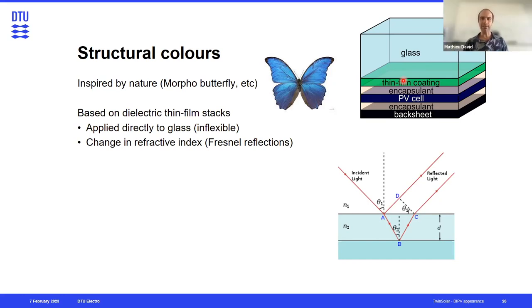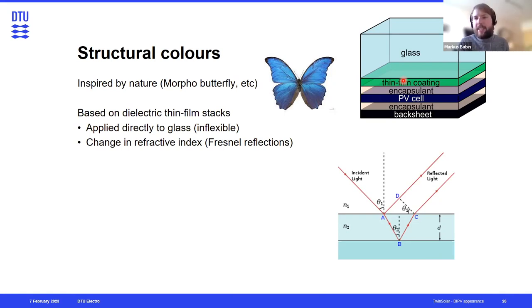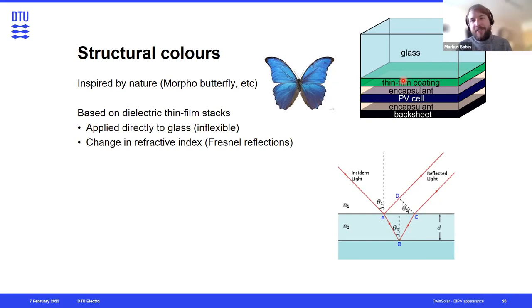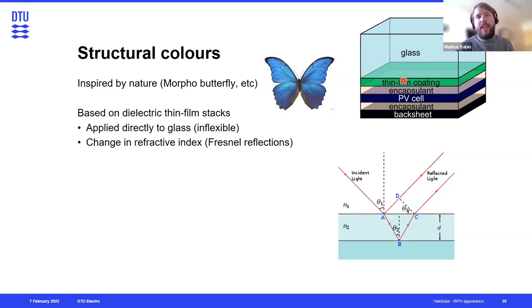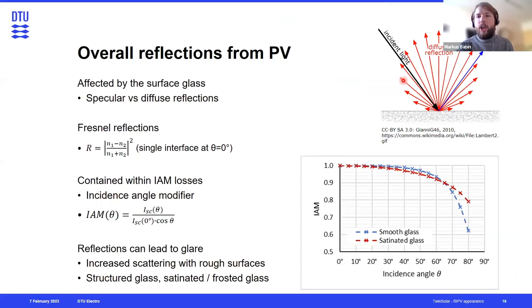Second question: a good glass-on-layer stack with glass, encapsulant, and so on has very high transparency and very low reflection — this is an ideal encapsulant. But are high transparency and low reflection opposite targets? I would say the target is less to have low reflections but rather to have low specular reflections. If you diffuse the reflection — scatter the light in multiple directions — then the reflections in a certain direction will be relatively low. You can achieve that with relatively low transmission losses, so you still achieve high transmission while scattering the light. I will show that after the break in the next presentation.